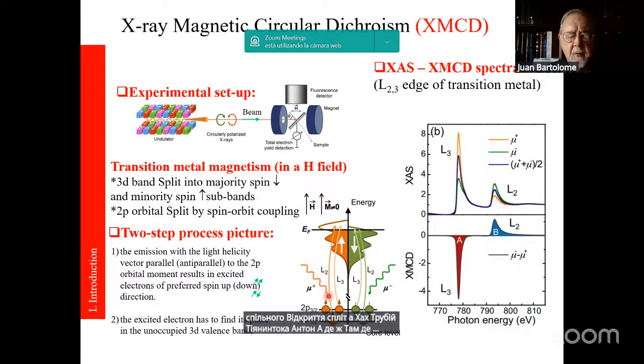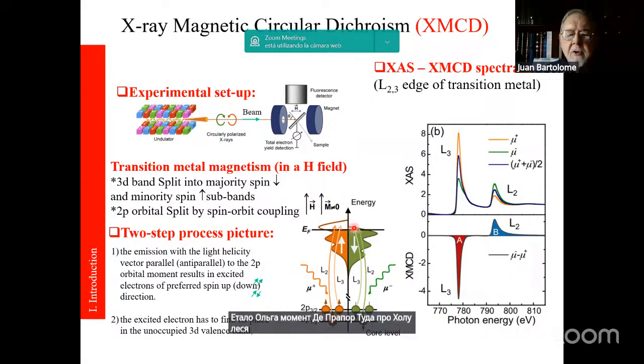So if we shine light with the light helicity vector parallel to the 2p orbital moment, for example, at the L3, the electron will be excited to the corresponding hole subband of the up spin orbitals. The same, but for left circularly polarized light, will excite the electron with the down orbital moment to the upper hole subband. How does this show up in the experiment?